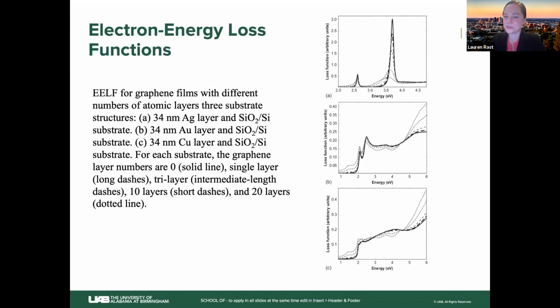So there's really a happy medium there, where a few layers of graphene can help mitigate losses and enhance coupling to the surface modes. And then beyond that, you get probably enhanced losses and dampening of peaks.